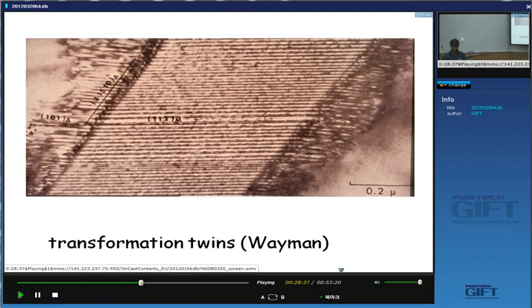The dislocations that you see in ordinary steels are because the shape change relaxes by plasticity. So if I look at the shape deformation, so this is my surface, and the formation of martensite will cause the surface to tilt like that. Yeah? Invariant plane strain. But if you are forming martensite at a relatively high temperature where both the parent and product phases are mechanically weak, then this deformation is very large and it cannot be sustained elastically.